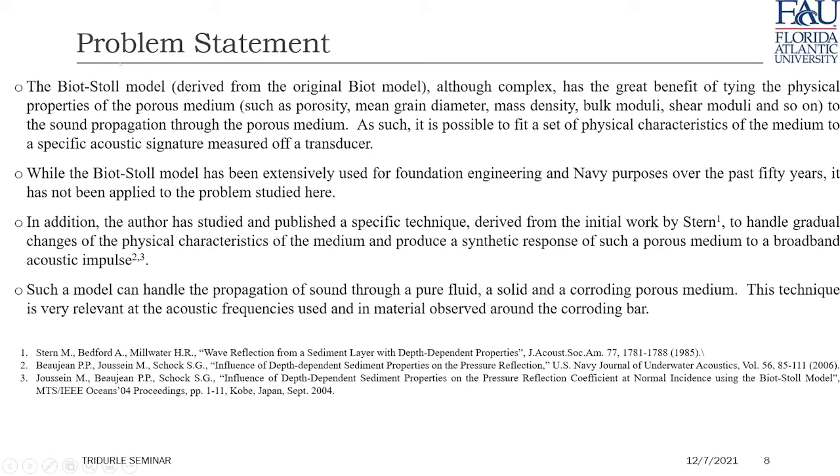Now, I am almost done with the background here. The Biot-Stoll model, although complex, has one great benefit: it ties the physical properties of the porous medium, such as porosity, mean grain diameter, mass density, bulk modulus, shear modulus, and so on, to sound propagation. It accounts for the tortuosity, for example, in the skeletal structure of the frame, and ties that to the sound propagation through the porous medium. So the idea is that it is possible to fit a set of physical characteristics of the medium to a specific acoustic signature measured by the transducer. It is a complex problem, but it is feasible.